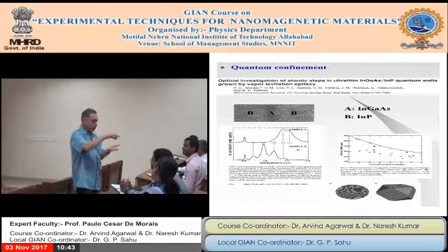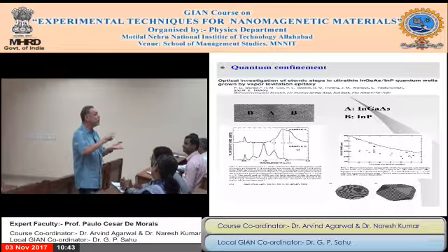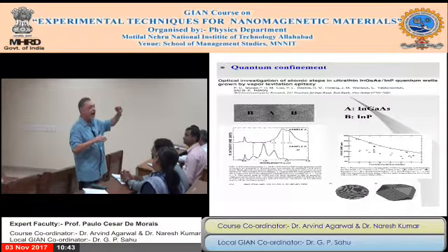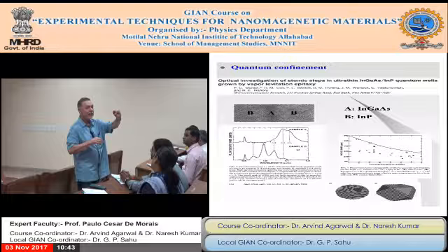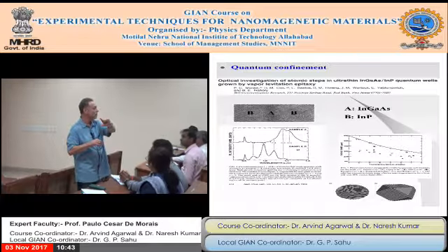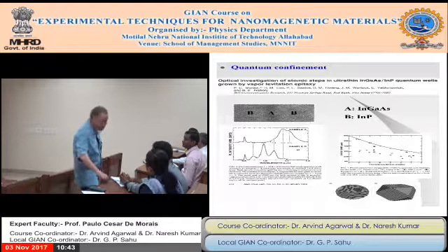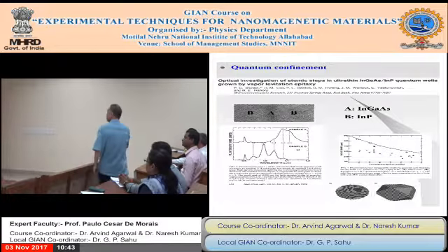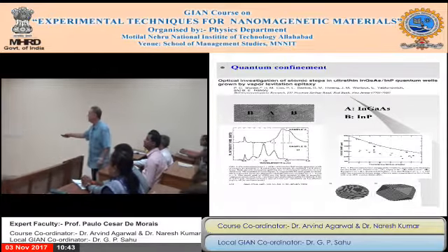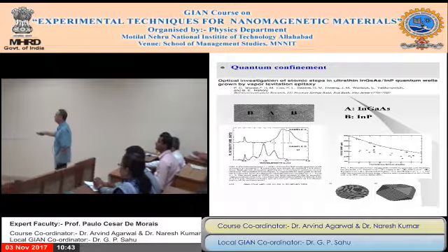I was able to scan the laser spot around the sample and collect regions where you had 2 atom layers, 3 atom layers, 4 atom layers, and took the spectrum. And here is the calculation. Here is the energy. What is that one?